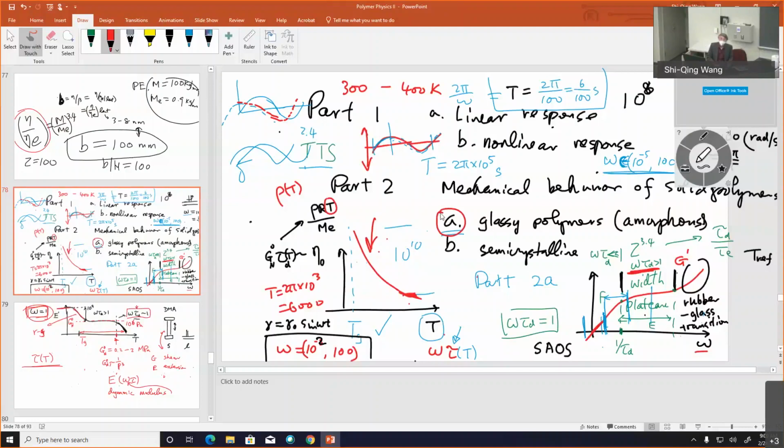If you have crystallization, and you just told me that you did this one, and you said to do the next one, you need to go lower temperature, right, to get the next decade. And you go there, boom, it crystallizes. Can you still do it there? Not really.